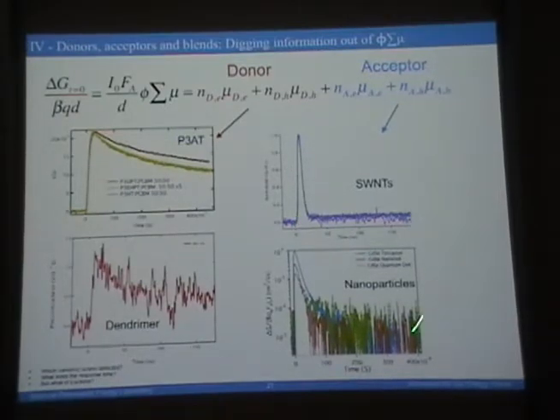And I was going to talk about some nanoparticle work. You can see a signal in neat nanoparticles, whether a dot, a rod, or a tetrapod. And at this moment, I don't know the origin of that signal. In theory, I should not be able to see anything. Because one of the features of carriers confined to a nanoparticle is if you confine the carriers too much, you lose their mobility. You start to make them resonate, and they bang into the ends of the particle. And so you lose your mobility. It's quite a simple model, but here you can see we're picking up a signal. We don't fully understand where it comes from.